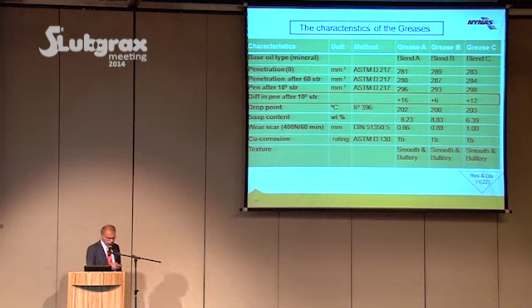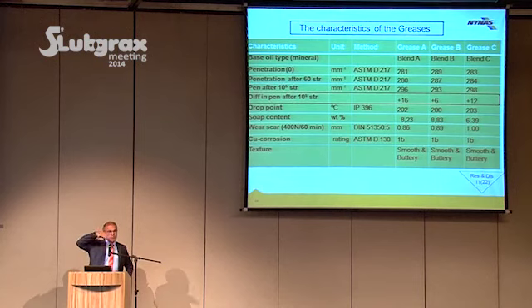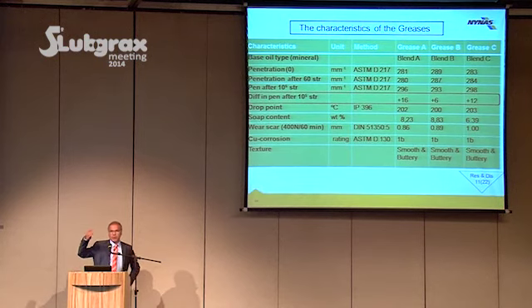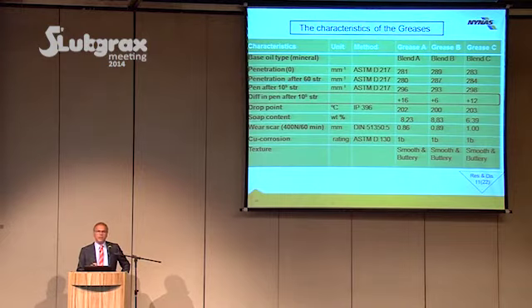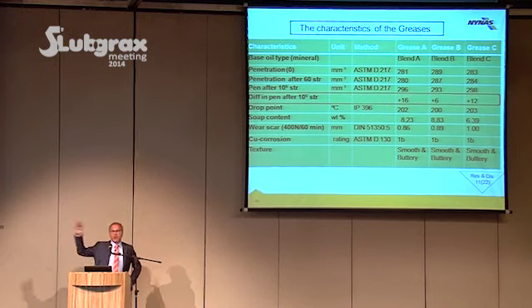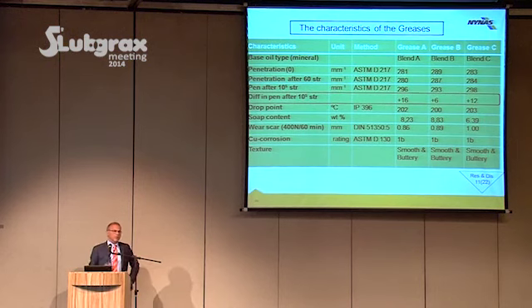What we see is that, first of all, the grease is quite stable, because of this number, penetration after 100,000 strokes. For those of you who are not aware of these test methods, it's a way to expose the grease to too much shear and see how much the grease, let's say, softens. So 100,000 means an enormous number. Probably after 50,000, you get the same result. But this is kind of a standard you have to follow.